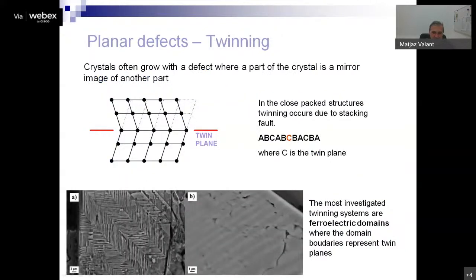Then there can be twinning. So twinning is typical for, let's say, ferroelectric or ferroelastic materials, when actually we don't change any symmetry, but we kind of mirror one crystal domain towards another crystal domain, as shown here. So we have a twin plane in between, and the mirror image of one crystal against the other crystal. So please remember this, because we're going to talk later also about the ferroelectric domains, where typically we meet such a situation.